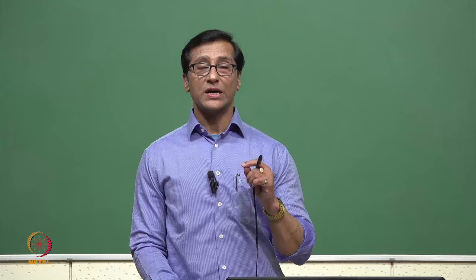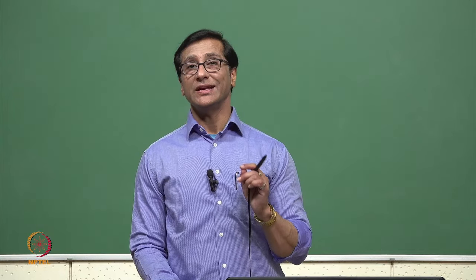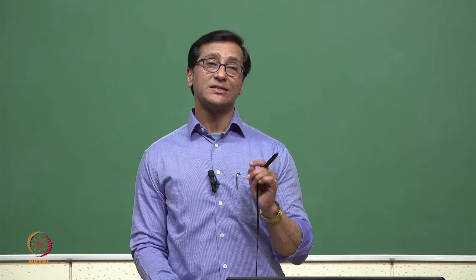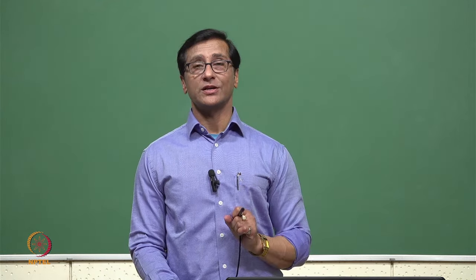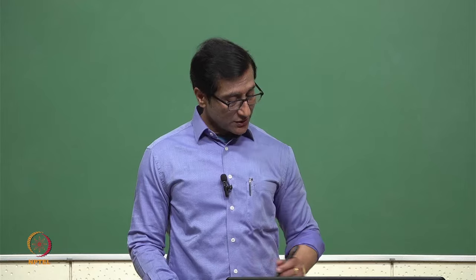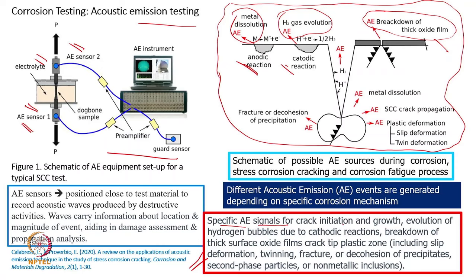So we can pinpoint what kind of fault we are getting, and we can adjust the process parameters in the right manner to avoid that kind of fault, and that is a major advantage of this. So that's why we say there are specific signals for crack initiation and growth, evolution of hydrogen bubbles due to the cathodic reaction, breakdown of the thick surface oxide layer, and particularly the plastic zone. In this case again there will be some further division possible, such as slip deformation, twinning, fracture, and decohesion of the precipitates, that is also possible.